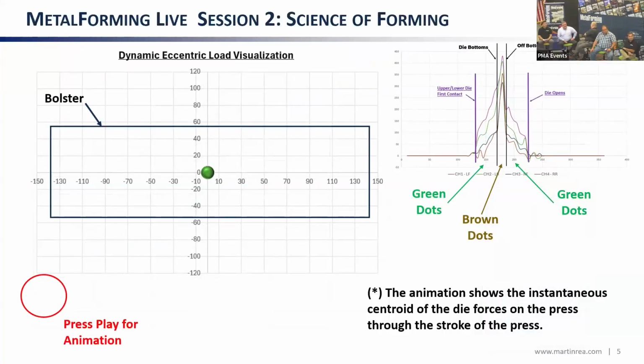When we take those same press curves, the blue dots were a static look at that press stroke. The animation I'll play is watching the centroid of the load move around on the bolster. There'll be a dark green dot for the current position, and then two different shades of lighter green following it, to give you an idea of the motion of the load on the bolster. When the dots change color to brown, that's when the die is on bottom. So you can see that even when the tool is on bottom, the centroid of the press force is not necessarily at the center of the press, and it's not necessarily stagnant.